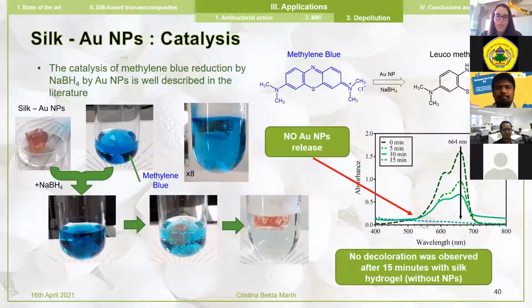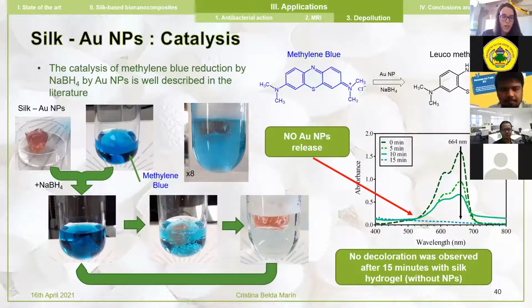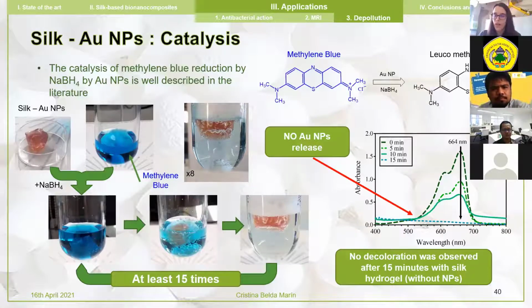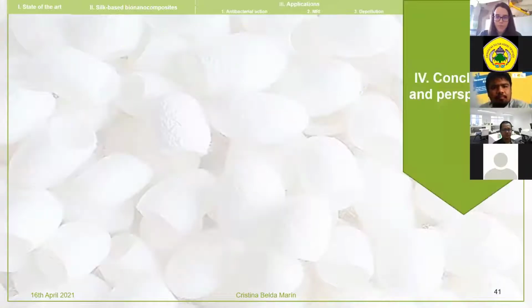Now the question was whether this procedure can be repeated. Of course, the hydrogel can be reutilized in a new methylene blue solution, and we have done this at least 15 times, obtaining the same results. So the material can be reused and recycled without a problem.